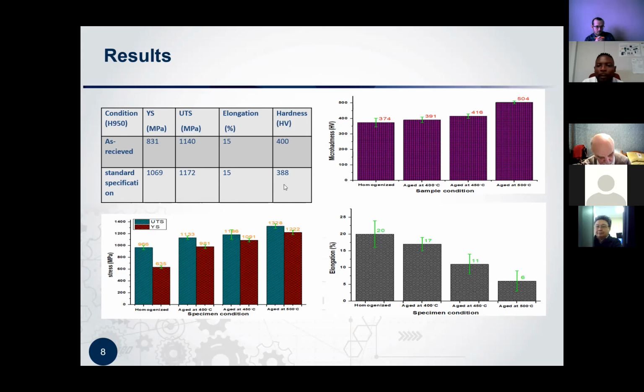So we had to move from 500 to 450. And from there as well, we couldn't find our optimum until we went to 400, which gave us better mechanical properties which are similar to that. What is more intriguing is that we were able to achieve these mechanical properties at lower temperature and also at a very minimum time. Remember, I said for the H950 condition, you age at 510, so it's about 100 degrees less, and also about 3.5 hours less, because we aged for 30 minutes, and then we were able to achieve more or less similar mechanical properties.